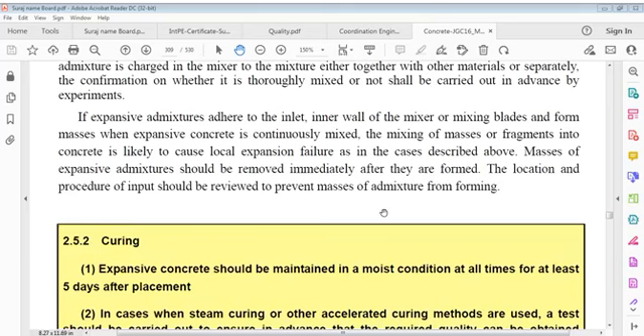Repeat. If expansive admixture adheres to the inlet, inner wall of the mixer or mixing blades and forms masses when expansive concrete is continuously mixed, mixing of masses or fragments into concrete is likely to cause local expansion failure, as in cases described above. Masses of expansive admixtures should be removed immediately after they are formed. Location and procedure of input should be reviewed to prevent masses of admixture from forming.